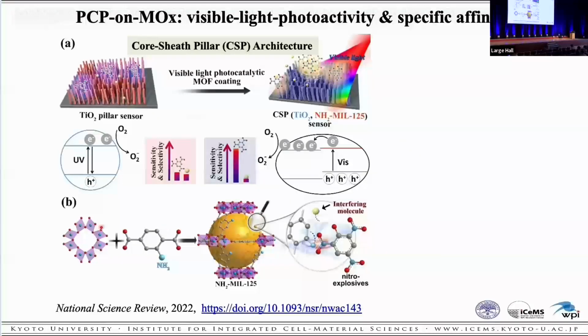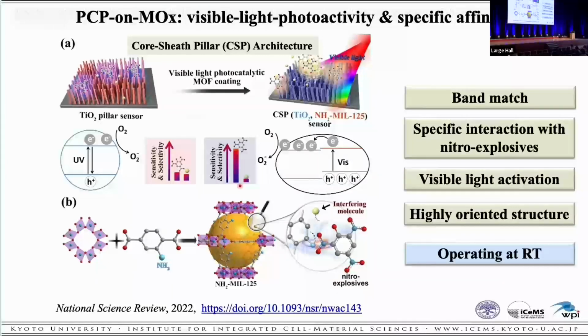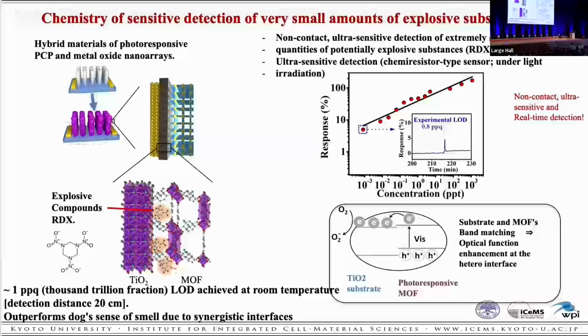So by using this unique core-shell architecture, we can detect the explosives. First, the capture of explosives at the MOF cage, and by illumination, by light, the excited electron is directly transferred to the titanium oxide, and also the oxygen reduction. So the sensing occurs. So all the processes can be realized in this system. So this material achieves the highest response to saturated RDX explosives vapor, 4.9 ppt, and lowest detectable concentration, 0.8 ppq among the reported chemoresistive materials.